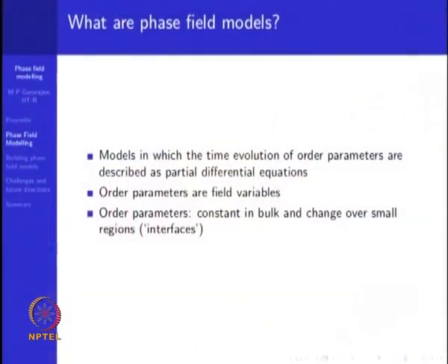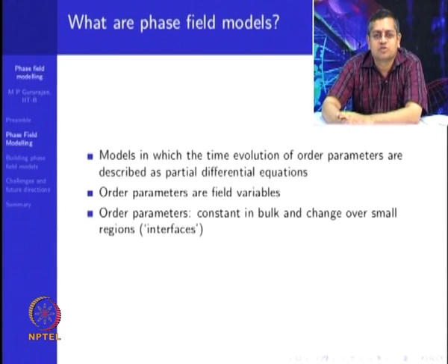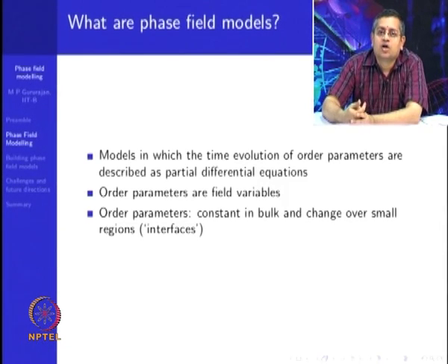Okay. Now, having said that, what are phase field models? So, here is an answer. Models in which the time evolution of order parameters is described as partial differential equations. That is a definition of a phase field model that you can use, because that is what we have been doing. We have been looking at the time evolution of the order parameters, and what do the order parameters do? They describe the microstructure. So, in this viewpoint, order parameters are field variables. That means they have a value for all positions in the domain for all times.